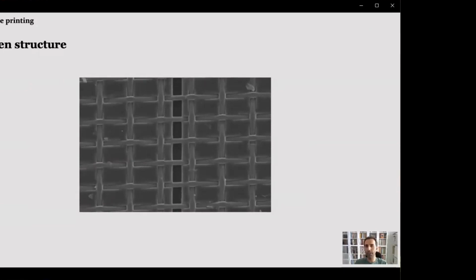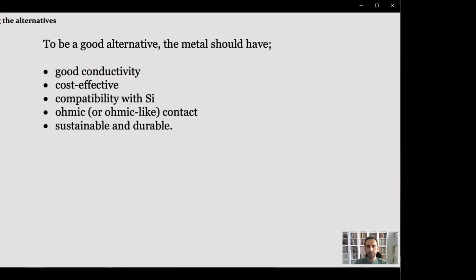ITRPV predicts to go lower than 15 micrometer finger width by 2030, so this approach can be improved and adapted by that time. After fine line printing, our second option is utilizing alternative metals such as nickel and copper. To do so, there are some criteria that these metals should meet. They should have a good conductivity, must be cheaper than silver, they need to work well with silicon substrates, and they should be durable. Most importantly, they should make an ohmic contact with silicon.